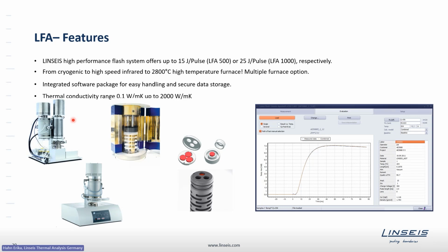Basically, this laser flash is able to measure insulation materials up to extremely high conductive materials. So summarized maybe 0.1 to 2000 watt per meter Kelvin. And this is a screenshot of the software, where you see the simple evaluation where the software does more or less all for you.